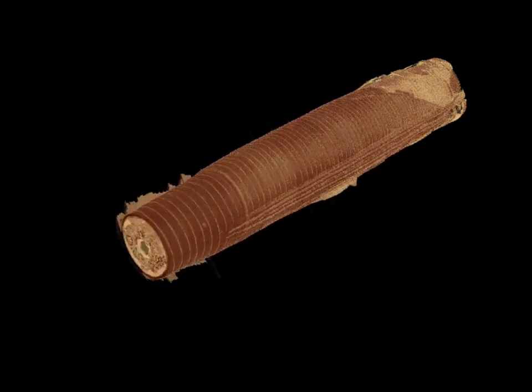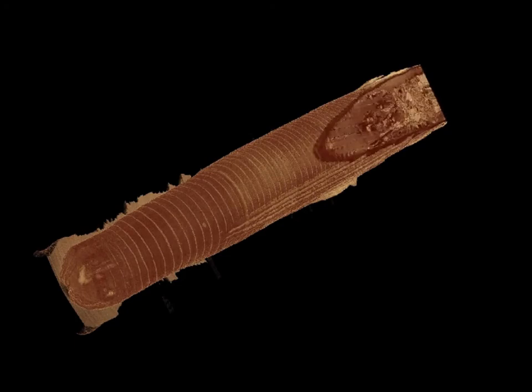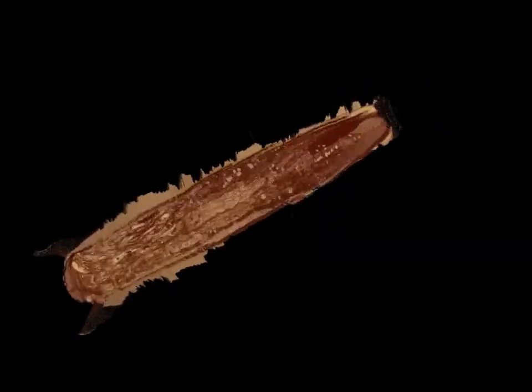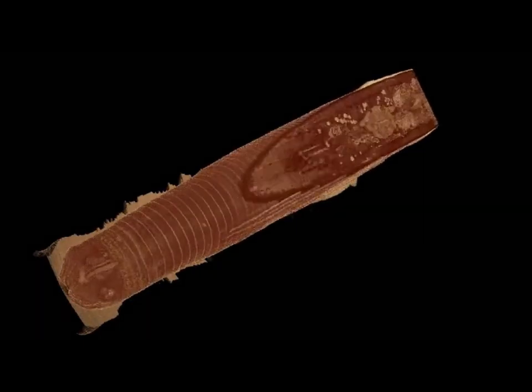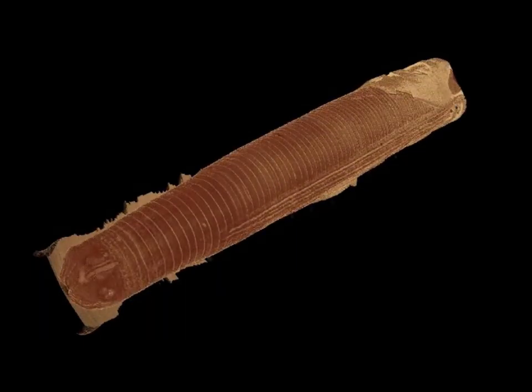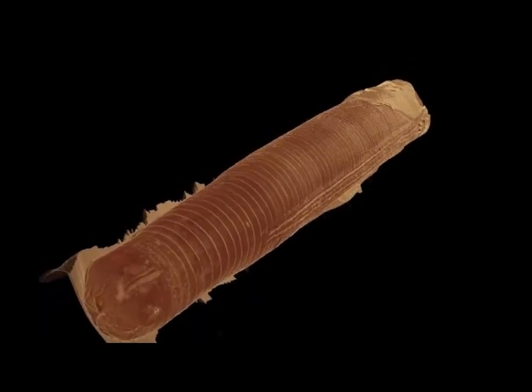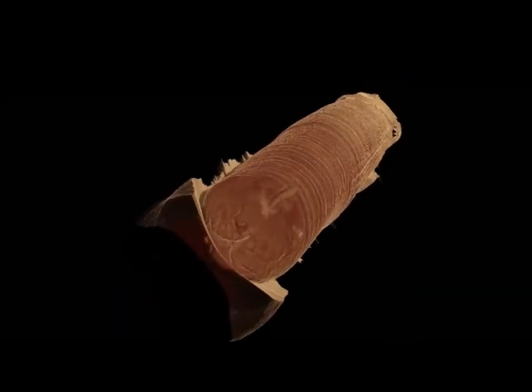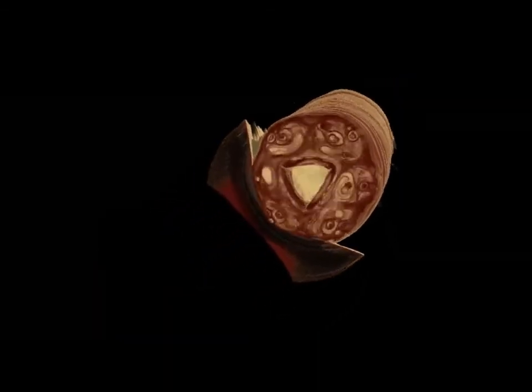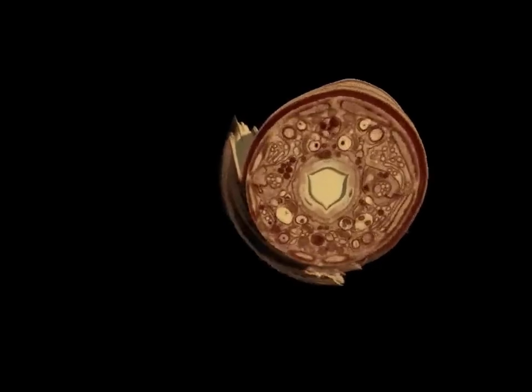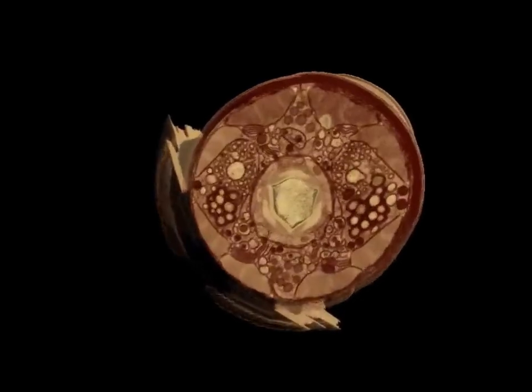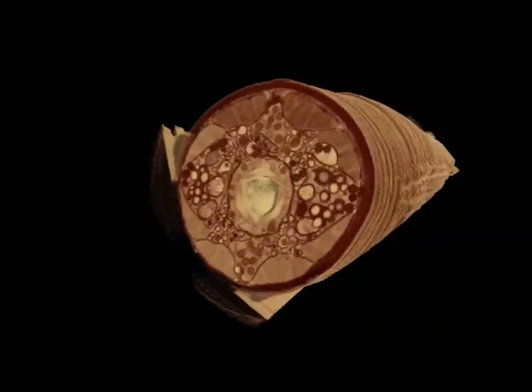This is also an interesting example. It shows a huge data set of a C. elegans worm. What is particularly impressive about this data set is that it contains over 10,000 sections, covering a length of more than 80 micrometers in Z direction. Not only could a constant slice thickness be achieved, but also all images are nicely focused and stigmated.